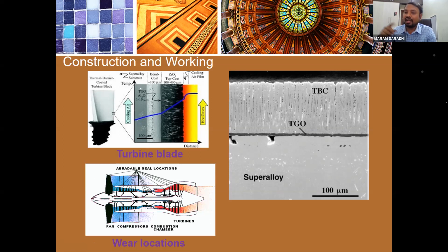If you want to have a highly rotating turbine with high power, you need to increase the temperature. If you increase the temperature, then the turbine blade will go bad. So there should be an optimum between the turbine blade and the temperature. By putting the ceramic coating, the temperature could be increased a lot. That is how people are working.